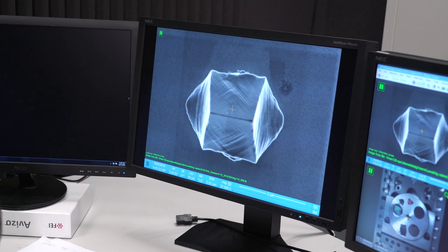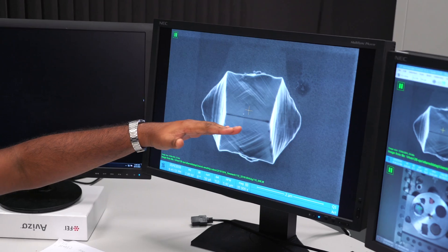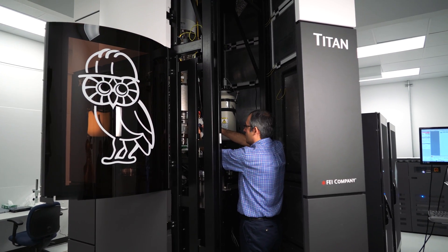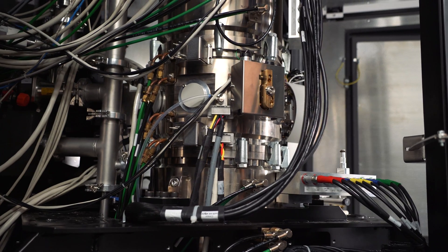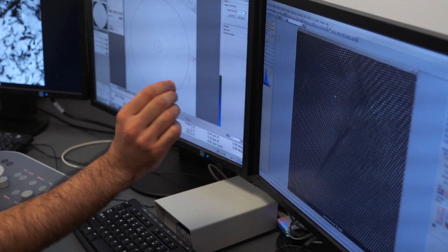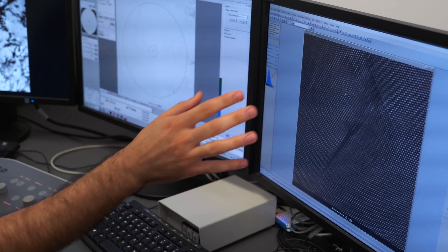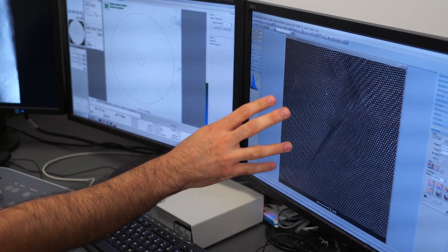This suggests some extreme events must have happened inside, so we'll take a very thin cross-section — about 100 nanometers — and look at it in the transmission electron microscope. What we see here is that silver atoms are rearranged and change in order to accommodate such a huge deformation by forming dislocations — many dislocations and different kinds of defects that we can see in these images.